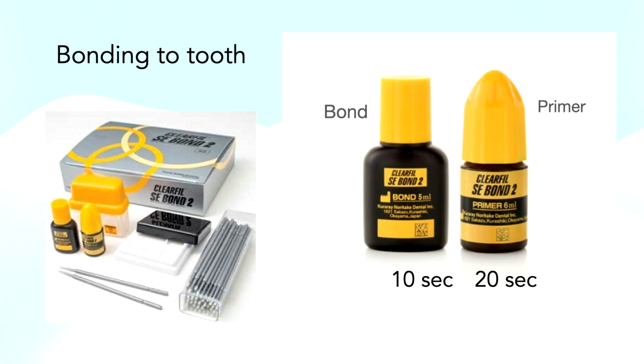Now, just as a sidebar, when you're using your air to thin the primer, and this is a water-based primer, and your tooth is what kind of base? Is it acetone or alcohol? Well, it's water too, which is nice. So you are evaporating some of the solvent, and depending on which version of Clearfil you're using, they went from alcohol to acetone to water, and I don't know what they're using now. But anyway, what you're trying to do is thin that layer down as much as you can. That's why you're using your air on it, and then light cure it.